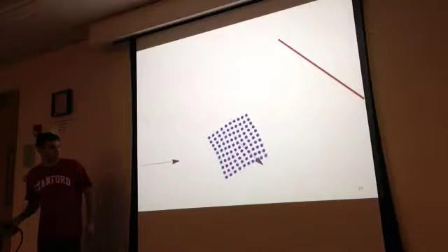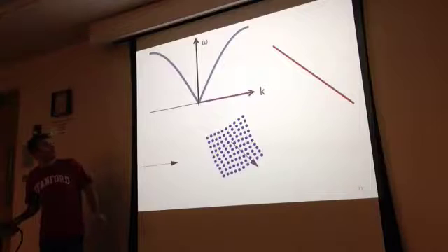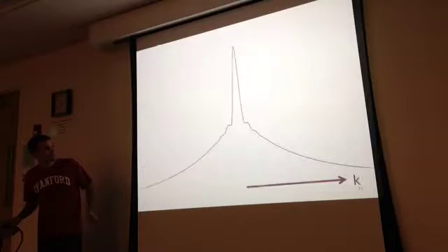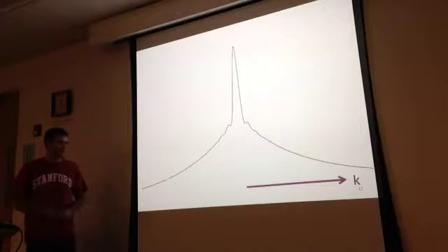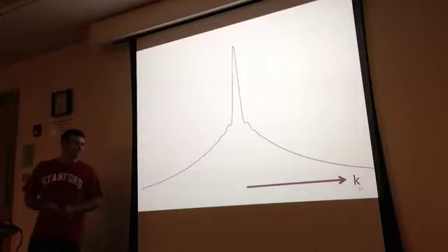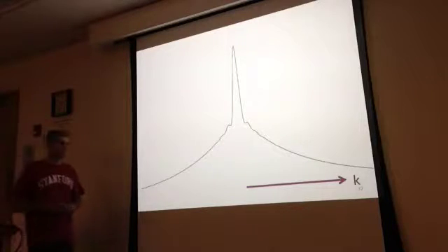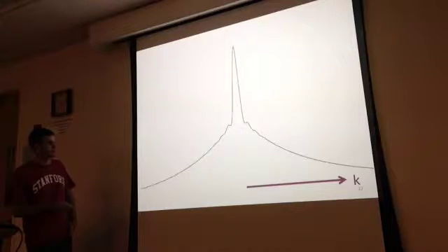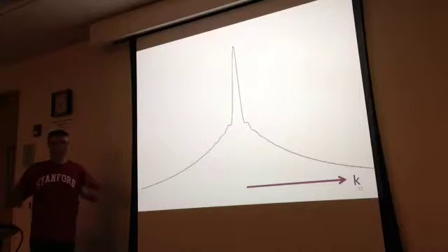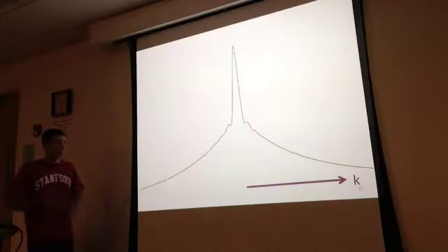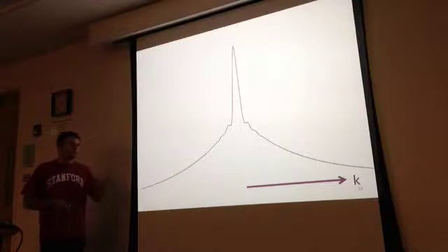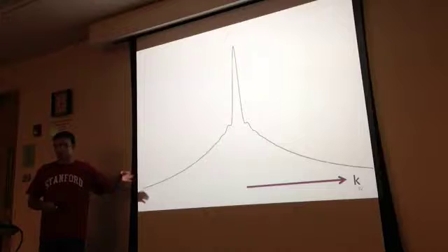Okay, so again, higher wave vector phonons are typically higher frequency than lower wave vector phonons, so our acoustic phonon dispersion might look something like this. On the next slide, I'm going to show you again this line detector. I want you to imagine that we've used something, perhaps a short 800 nanometer pump pulse, for instance, to excite a whole continuum of phonon modes all at the same time in this crystal. What you're seeing in this diffraction pattern is we still have the Bragg peak in the middle, and these wings represent a continuum of side peaks because we've displaced a continuum of phonon modes of many different wave vectors. And we want to know, now that the laser is gone, how is this picture going to evolve?